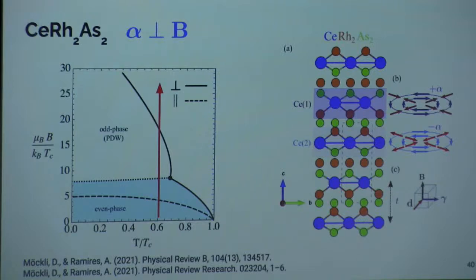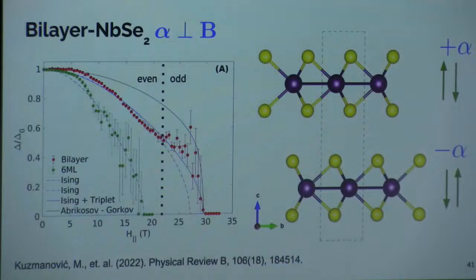Because of the crystal environment, each sublattice experiences a Rashba spin-orbit coupling, which has a helical in-plane texture. So both sublattices have this texture, but in opposite direction. So this leads to an intriguing phase diagram, which I will explain shortly. A similar situation happens in bilayer niobium diselenide. So here, instead of a sublattice, I have different layers. And instead of Rashba spin-orbit coupling, I have Ising spin-orbit coupling.